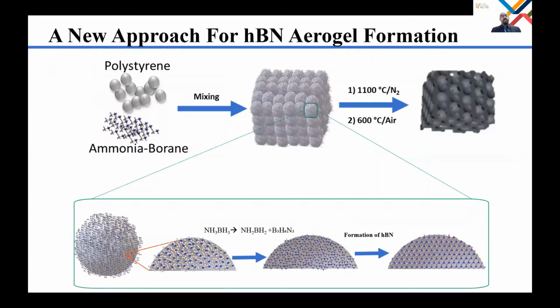Toward this aim, here we use solid ammonia borane as a precursor and polystyrene nanoparticles as a template. Mixing ammonia borane and polystyrene nanoparticles leads to the formation of a self-assembled hybrid nanocomposite of ammonia borane and polystyrene. The key here is that ammonia borane adsorbs on the surface of polystyrene nanoparticles because of intermolecular interactions between ammonia borane and polystyrene nanoparticles.